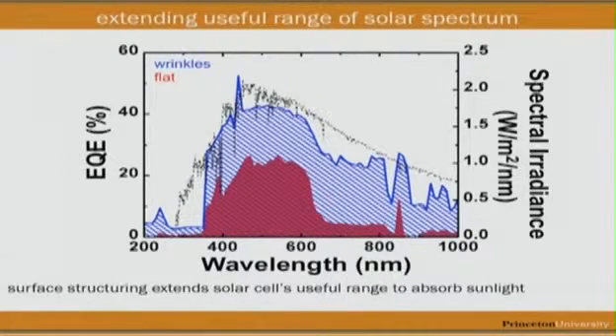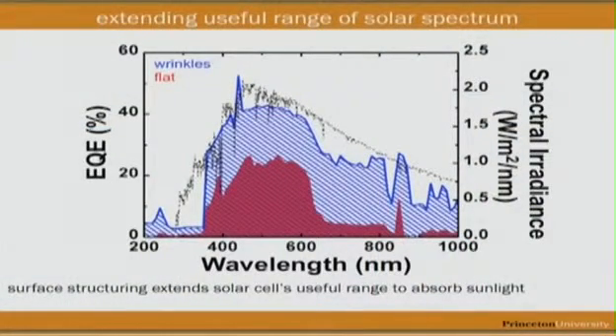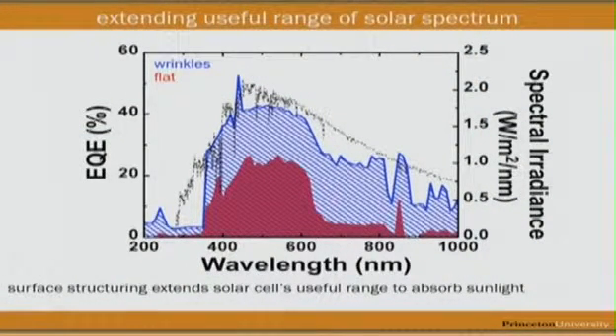If we look at the external quantum efficiency, the efficiency at individual wavelengths, of the device on the flat surface, you see that there's a sharp drop. This sharp drop is due to the band gap of the P3HT polymer. It's an inherent materials property. You can't run away from that. But now if you look at the device that we built on the wrinkled surface, that looks very different. You can see non-negligible, actually substantial photocurrent generation beyond that edge. And for those of you who make solar cells, that's because we believe we're directly exciting the charge transfer complex.